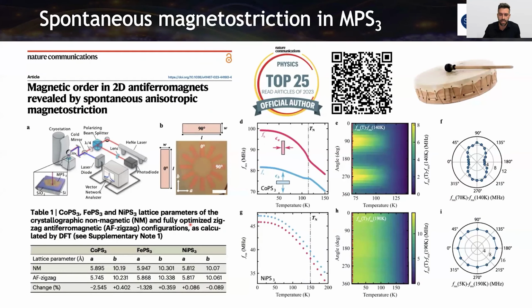Then other calculations we did for these materials, in this case for cobalt, iron, and nickel PS3. This is in collaboration with the group of Van der Zant in Delft University. And in this case, we predicted with the DFT calculation. So here we are fully optimizing the structure of cobalt, iron, and nickel. And we can observe a 2.5% compression of the a-axis, and a little expansion of the b-axis. This is also happening for the iron, but for the nickel nothing is happening. There's no expansion or compression.